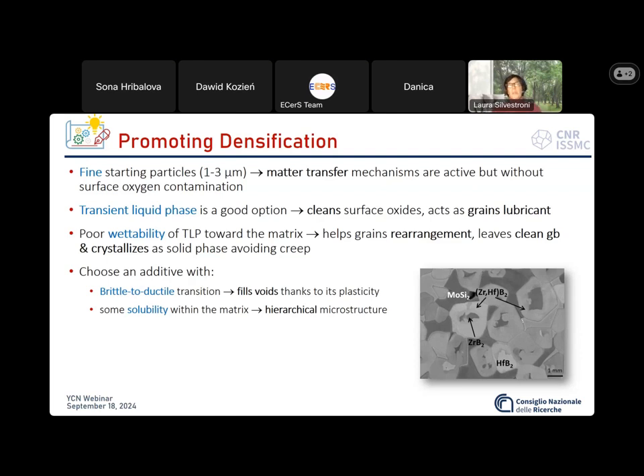So our selection fell on molybdenum silicide because it has a brittle to ductile transition, which is ductile and fills the voids due to its plasticity, and it also had some solubility within the matrix, so that we could form some core-shell structures and hierarchical microstructure that you will see in the next slides.